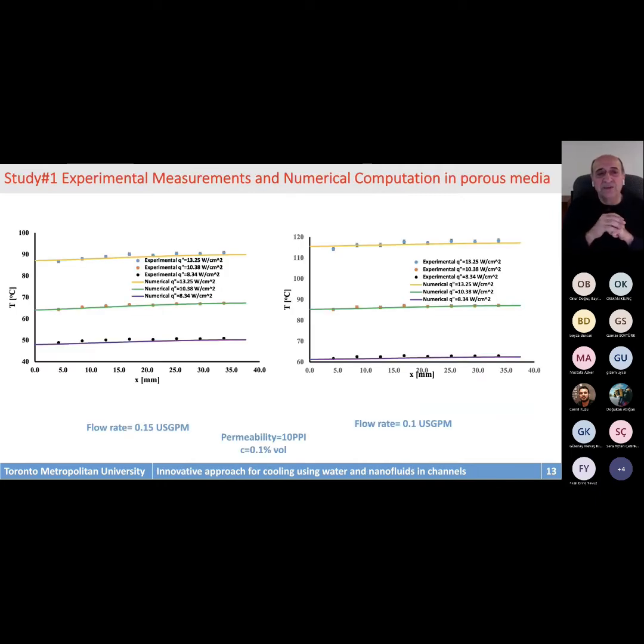Now, with respect to study number 1, we did some experimental measurements for different heat fluxes. To remind you what study number 1 is, it was a porous block. And this porous material, you can buy it from industry, and they have a porosity of 0.91, and they have a different permeability depending on what you need. So we selected 10 PPI, 20 PPI, or 40 pores per inch. And we did it for different flow rates.